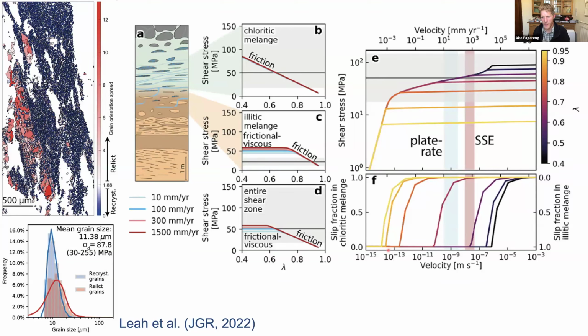At the same time, you see a change with velocity: the faster we go, the more slip is in the chloritic melange, which is frictionally weaker, versus the illitic melange, which deforms more easily by pressure solution. So in this place, the structures kind of look like that too. You have lots of frictional surfaces in the chlorite and distributed shear in the illitic melange.